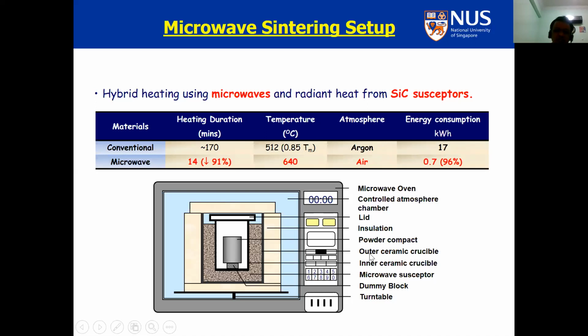So this is how it works. Switch on the microwave, the microwave heats the susceptor, which heats the billet from outside to inside, and the microwave heats the billet from inside to outside. So there are 2 heating fronts, inside to outside, outside to inside. And that is very effective in giving a homogeneous temperature distribution and a homogeneous microstructure of the billet.